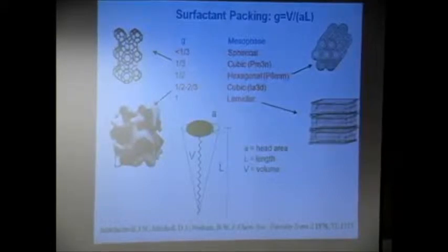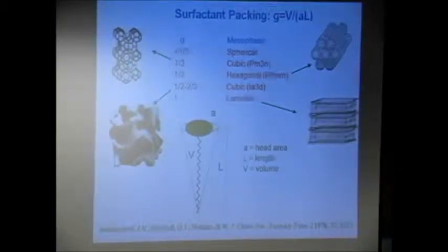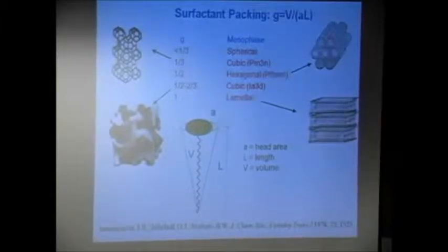What eventually happened after the initial announcement is many people entered the field, and they realized that the type of structure that you get out, or the pore structure, the three-dimensional array of pores, depended on what was called the surfactant packing parameter. So shown here schematically is a surfactant micelle with a polar head group that's wetted by the water phase. And this is the hydrophobe linkage or tail that self-aggregates to form a micelle.